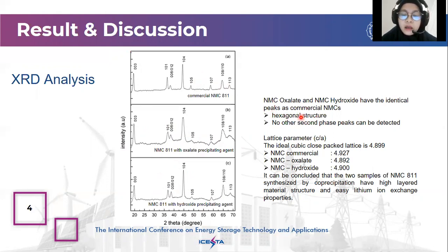All samples have a hexagonal structure, which is classified as a layered material in the R3M space group. NMC oxalate and hydroxide were successfully synthesized with no secondary phase detected. So it can be concluded that the NMC material is free from impurities. From the analysis of the diffraction peak, it can be seen that the lattice parameter of each precursor,